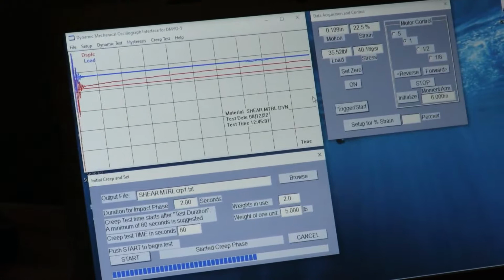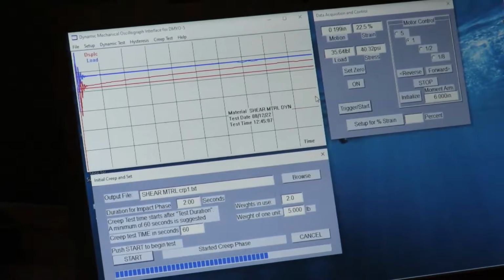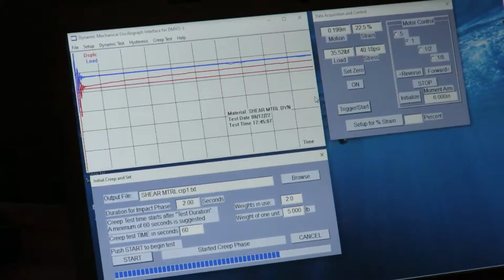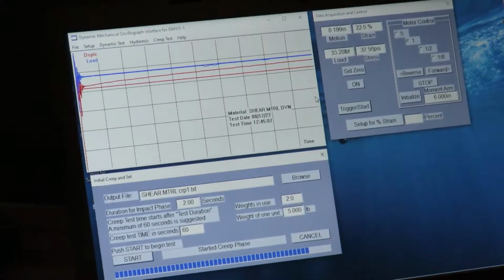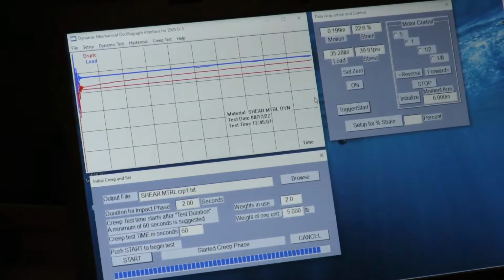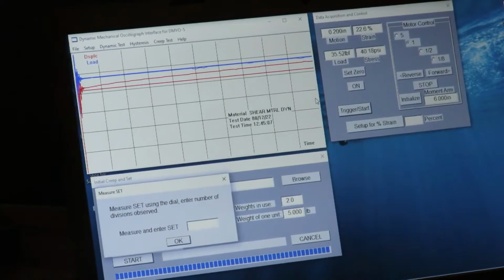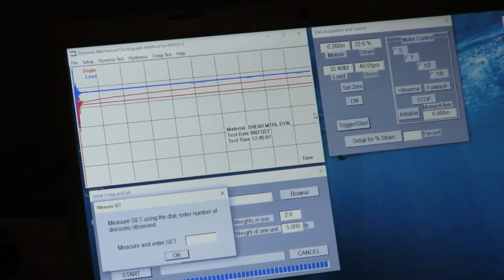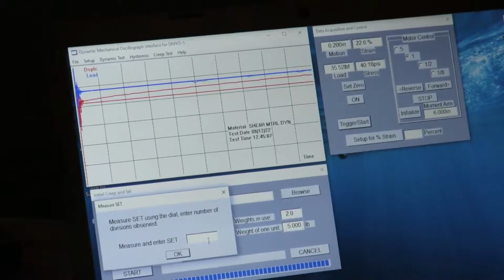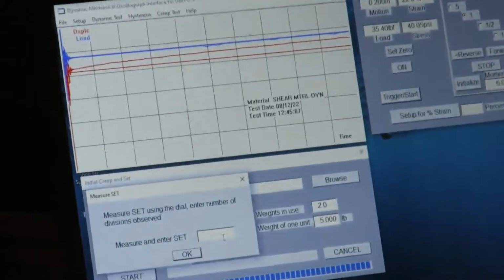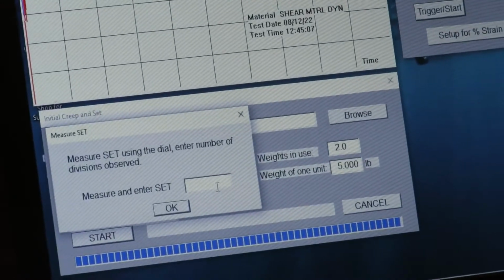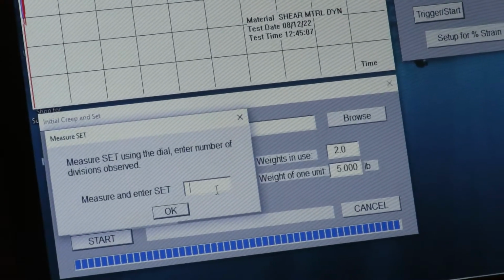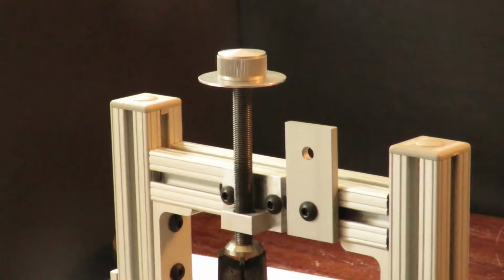Creep is very important for products that go into constant strain, constant stress situations under weight, such as heavy loads, seals, and anything that seals a product from ambient conditions has to be designed for good creep properties. At this point, we have to measure the compression set and include that in this calculation. And the dial here gives us the compression set measurements.